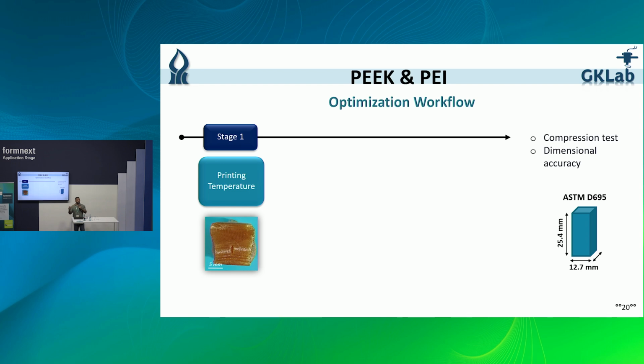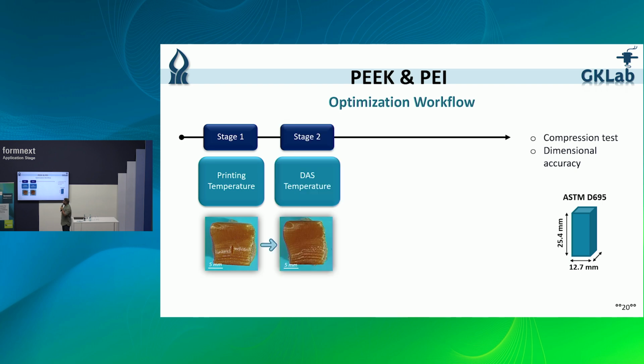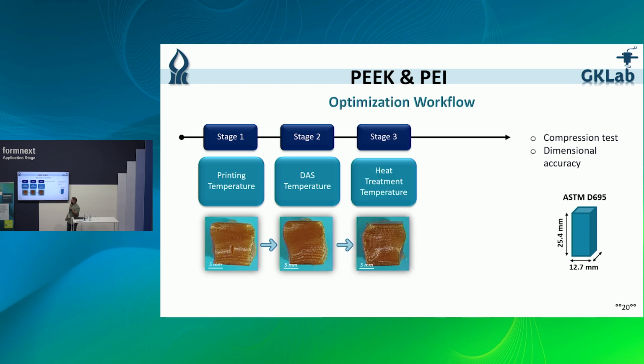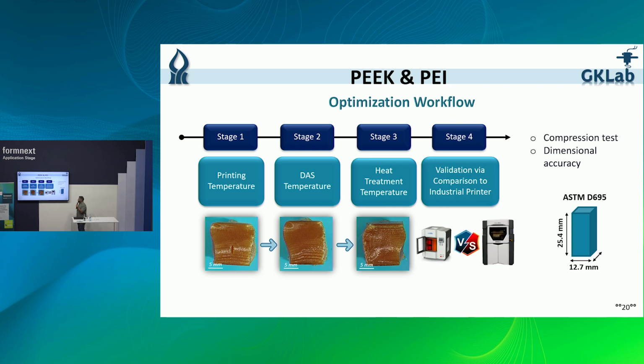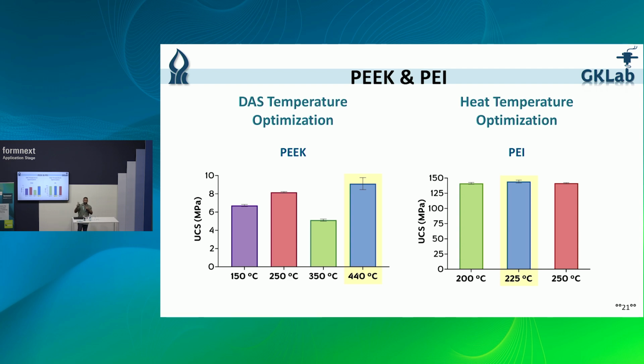And for that we conducted an optimization workflow, or optimization process, that is constructed of 4 stages. In the first stage, we optimize the printing temperature. In the second stage, we optimize the DAS, or the convection heating temperature, with the printing temperature from the first stage, then the heat treatment temperature, and finally, we validate our results by comparing our optimized parts with parts manufactured on an industrial grade printer. Here you can see an example from 2 different stages for each of the polymers. We achieved optimal ultimate compressive stress for a DAS temperature of 440 degrees Celsius for the PEEK, and an optimal ultimate compressive stress at a heat treatment temperature of 225 degrees Celsius.